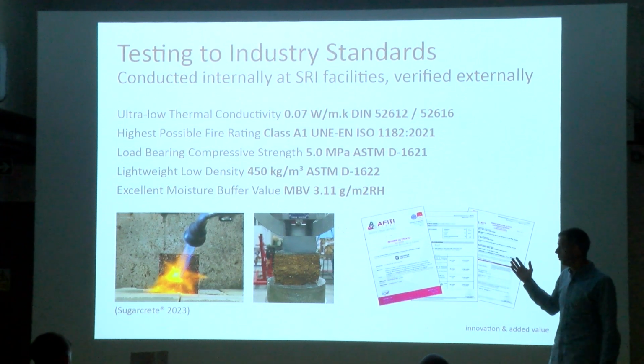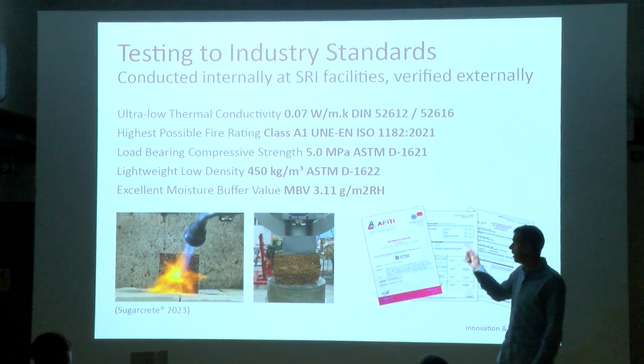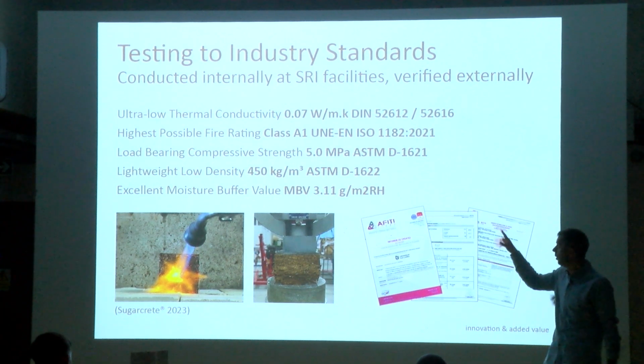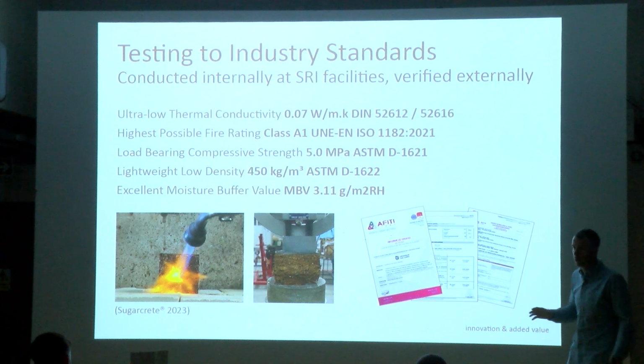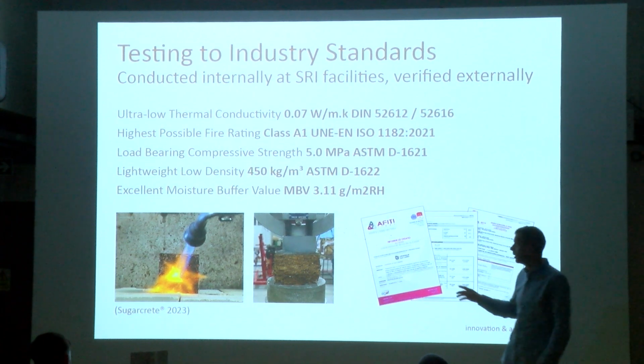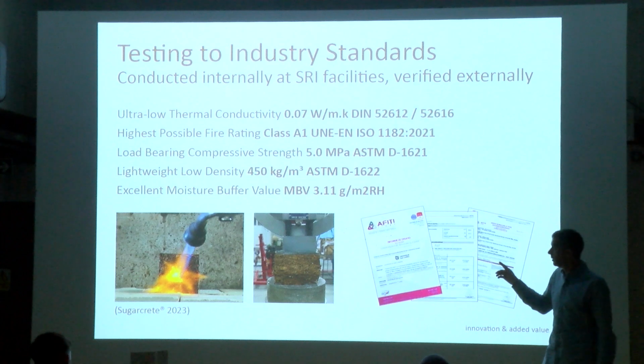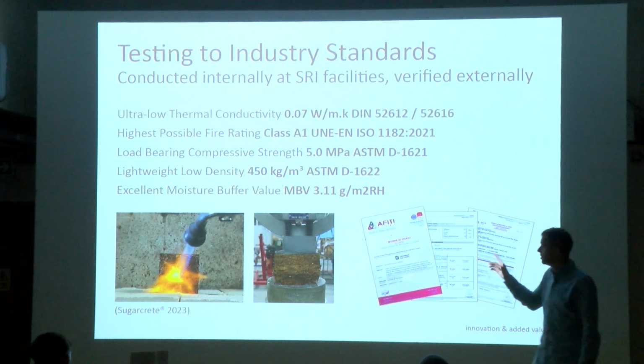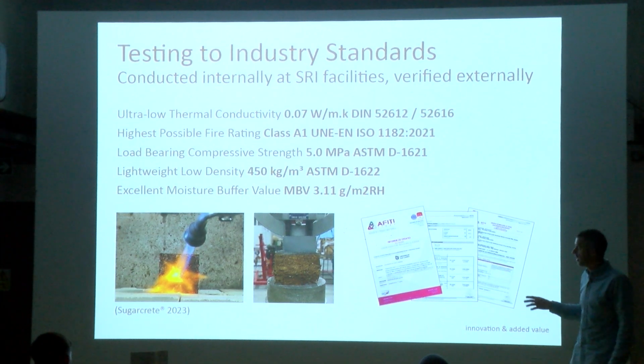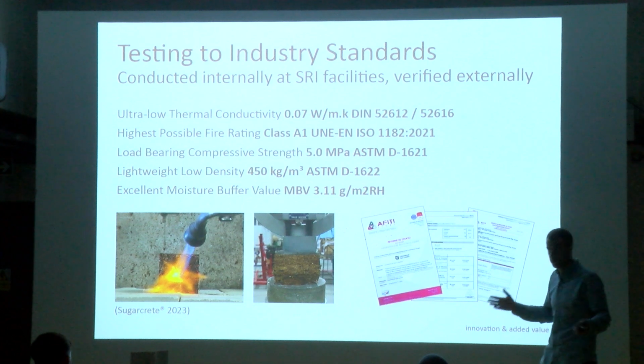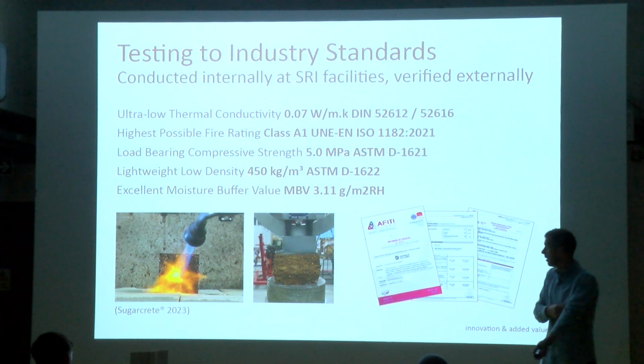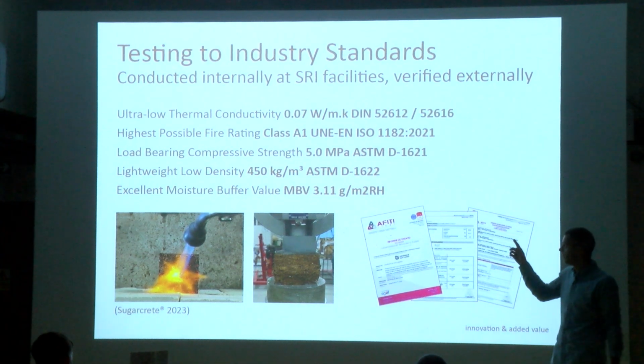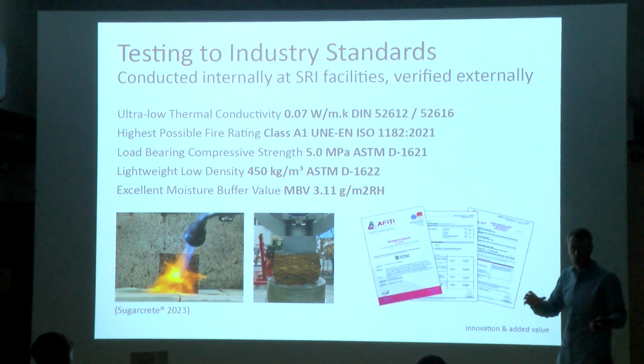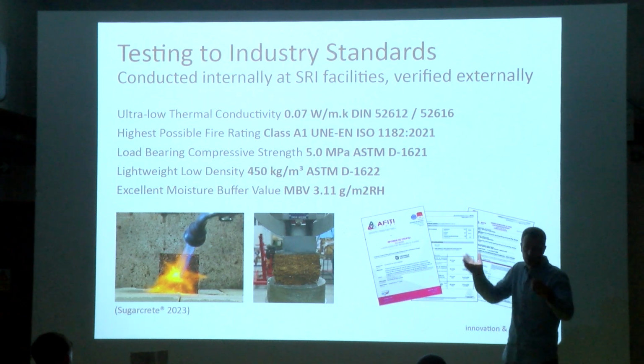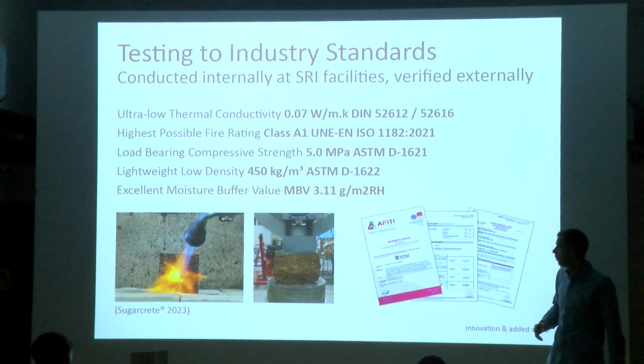And the main testing that we have been doing, they have to do with the thermal conductivity, and it's been proven to have very low thermal conductivity, 0.07, 0.08, comparable to straw, cork. The highest possible fire rating, due to the binders that we are using, we have achieved class A1 on fire rating, which means that you can use it anywhere, both for cladding and for structure. We have managed to achieve a compressive strength of 5 megapascals, which is comparable to concrete blocks, which allows you to have load-bearing and non-load-bearing walls.